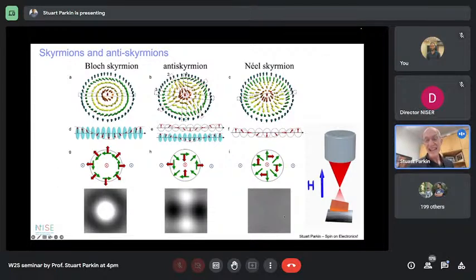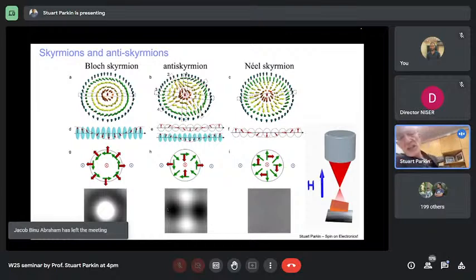And on the right-hand side, in a Néel skyrmion, it turns out that because the magnetic moments in the domain wall are oriented parallel to the radius, as shown in this cartoon, the Lorentz forces are around the circumference, and basically there's no change in the nature of the electron beam. It's just that the electrons are rotated. And finally, in the anti-skyrmion, we calculated this is what we would expect to see.